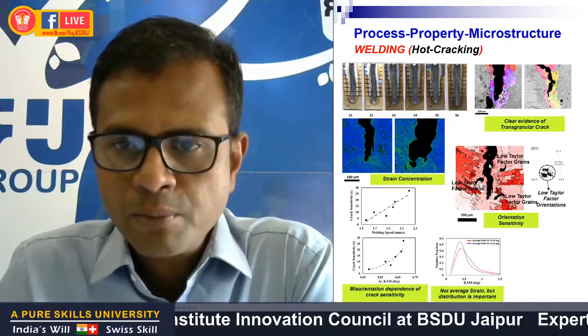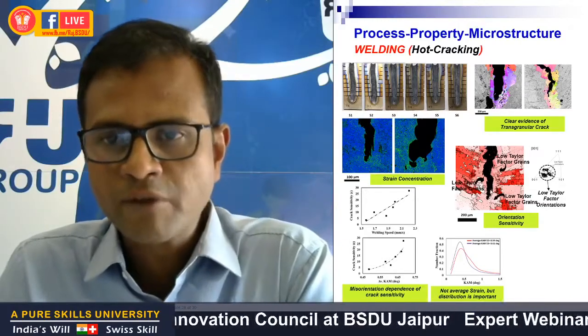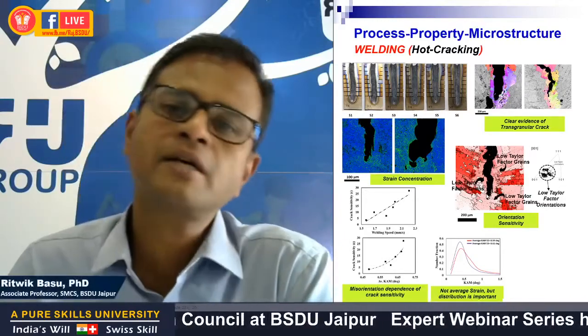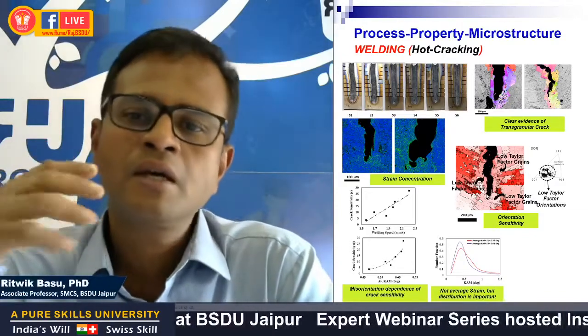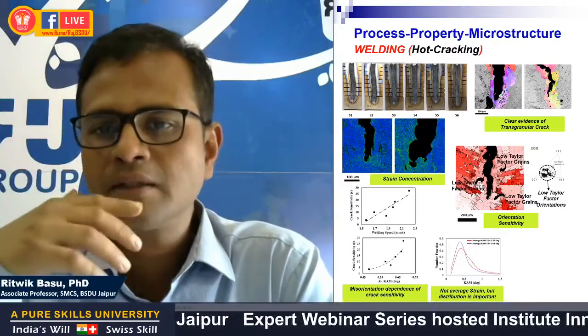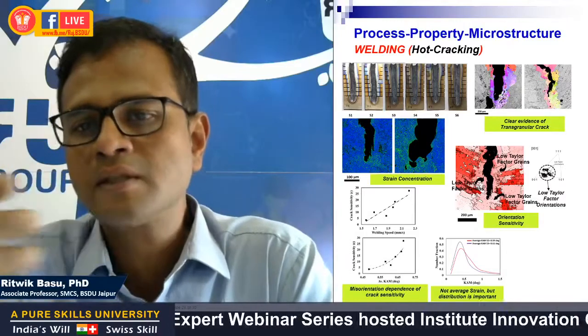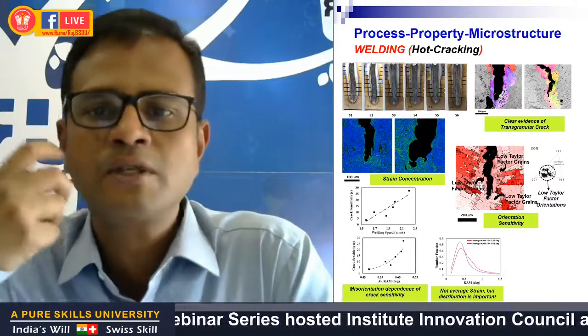So the cracks were seen to propagate mostly through the low Taylor factor grains, so the softer grains that had orientation suitable for slip activation, and the crack propagation was mainly assisted by deformation slip around the plastic zone of the crack tip.